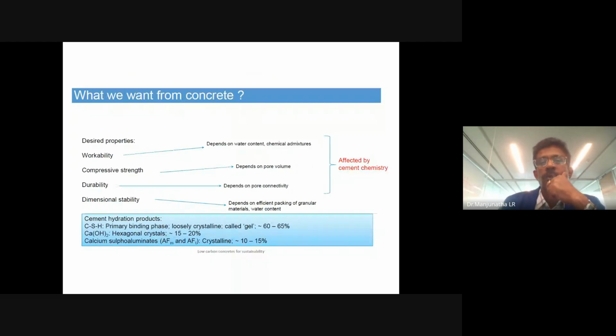So as I told you, we want so many things from concrete. Even though concrete is considered an inert material, it is not an inert material. It is a very active material. It will keep on hydrating even after 1 year if you are using a mineral admixture like GGBS or fly ash. When we make concrete, in the initial workable stage, it should be highly workable. That means it should be able to flow freely and should not segregate and bleed. So workability is very important. Compressive strength is important. Durability and dimensional stability are important. We are looking for dimensional stability and durability. These are all very important for a concrete structure.